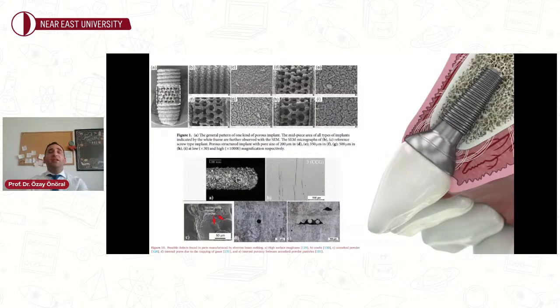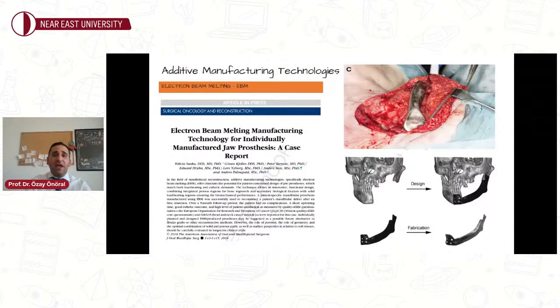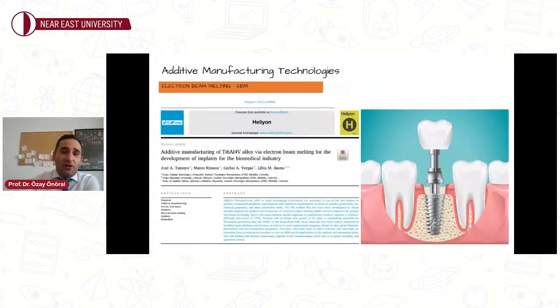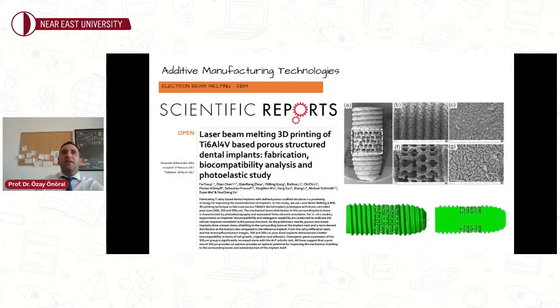Electron beam melting, unfortunately, has a single material option, I mean metals, metallic powders. But it is a good choice for the fabrication of dental implants, as you see in the slideshow. Here again, an electron beam melted printed partial mandible, I mean part of the lower jaw, was implemented for rehabilitation of the defect. And there are a number of studies targeting electron beam melting fabricated dental implants, as you see in this slide and also in this slide. They are working on it.